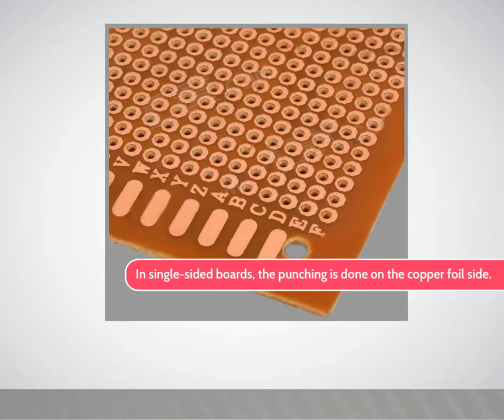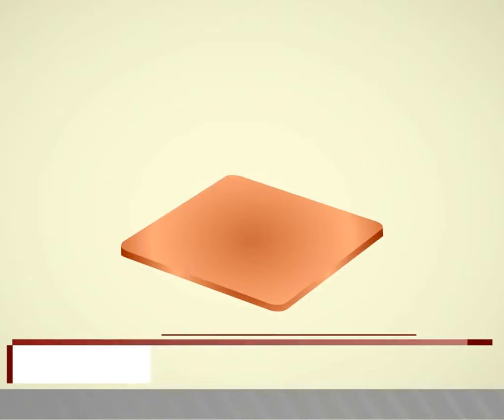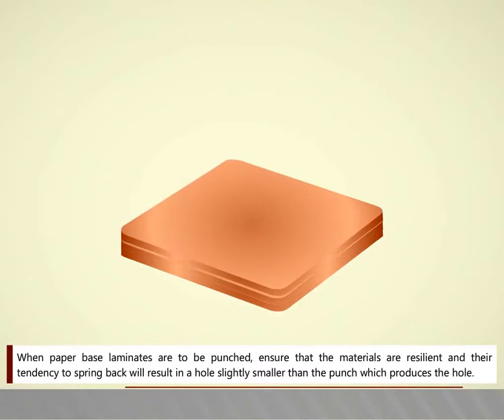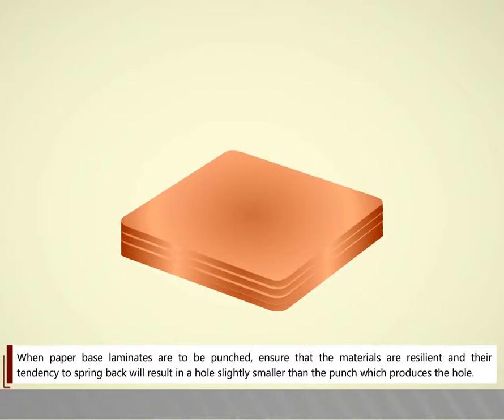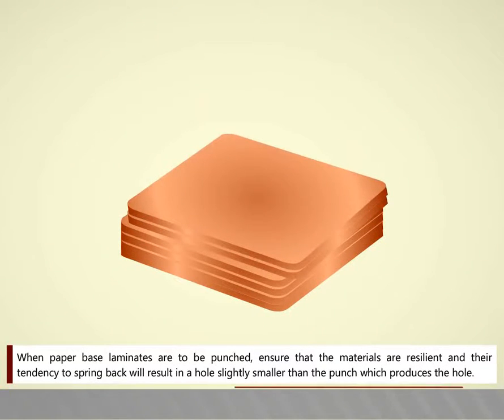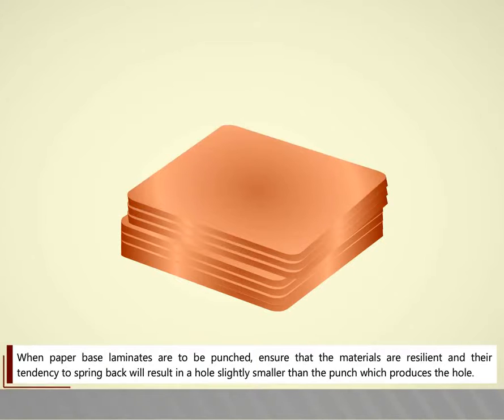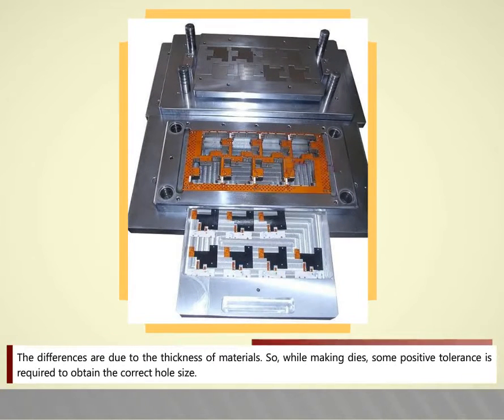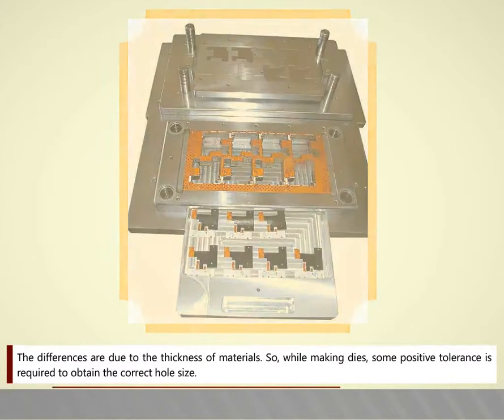In single-sided boards, the punching is done on the copper foil side. When paper-based laminates are to be punched, ensure that the materials are resilient, and their tendency to spring back will result in a hole slightly smaller than the punch which produces the hole. The differences are due to the thickness of materials. So while making dies, some positive tolerance is required to obtain the correct hole size.